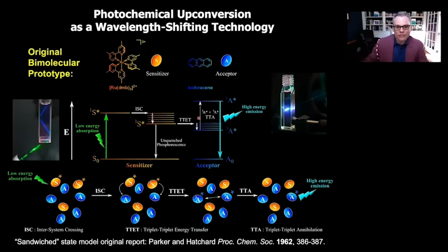So if we swing back to the original systems that we were looking at, we have this ruthenium metal to ligand charge transfer photosensitizer and just anthracene as a triplet acceptor. If you compare the Jablonski diagrams, it becomes very obvious how you design a photochemical upconversion donor acceptor pair. What you want is to sandwich the singlet and triplet levels of the sensitizer in between those of the molecule that's going to serve as the acceptor annihilator. That's really the critical feature.